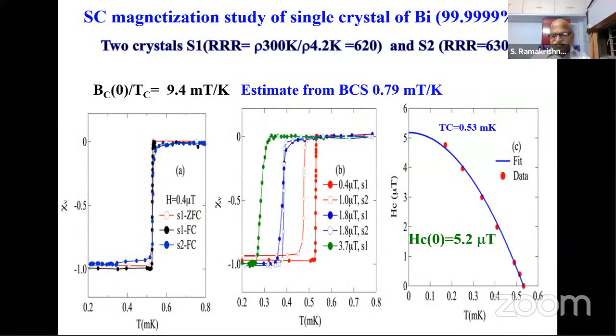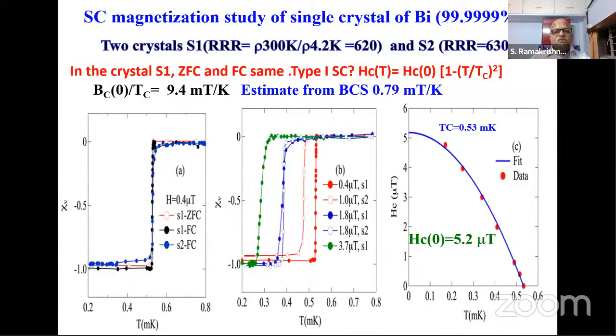And so we started working with bismuth. We took two crystals and you see that the magnetization is showing diamagnetism. Also this diamagnetism as a function of field decreases as it goes to lower and lower temperatures. Then you can see the critical field as a function of temperature. The extrapolated value of this critical field is about 5.2 microtesla, almost 1/10 of the Earth's magnetic field. So if the Earth's magnetic field is present, you will never see the superconductivity of bismuth.